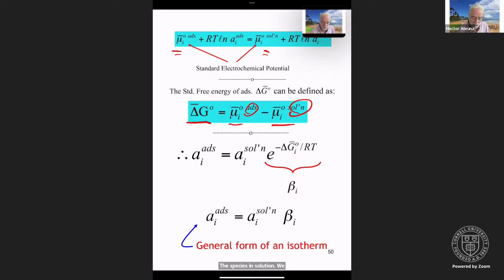We can then go back and say the activity of the adsorbed species is the activity in solution multiplied by this beta factor, which takes into account the free energy of adsorption relative to the thermal pool. And so we can write that the activity of the adsorbed species equals the activity in solution times this beta factor. And this is the general form of an isotherm. And notice we have made absolutely no assumptions in here. And we're using activities. I mean, we could in principle say that this is a concentration, but the thermodynamically relevant parameter is activity, not concentration.